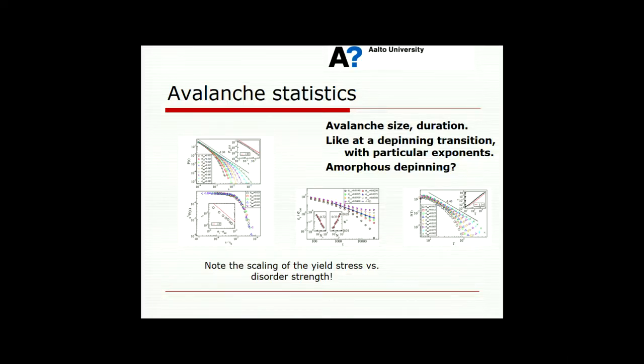Just to show what this stuff actually looks like, here are these avalanche size distributions. At the end of the day, you can collapse all of this as a function of external stress, such that you can also look at how the cutoff scales as a function of distance to a critical yield stress. So this model, if you put enough disorder, the disorder combines with the dislocation self-interaction in such a way that you have a real yielding point, not what I was talking about previously.